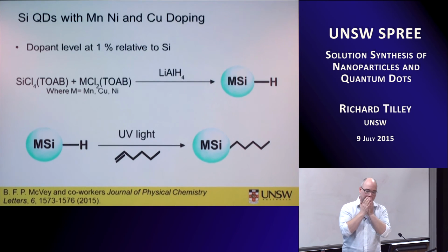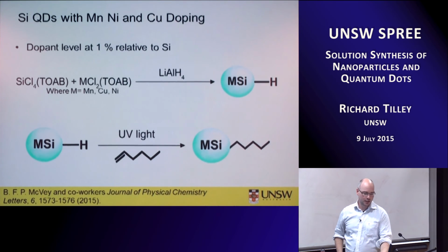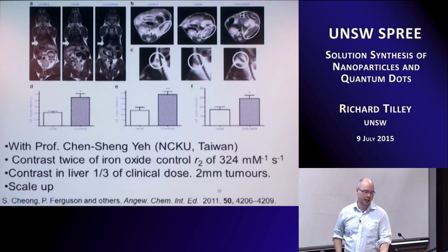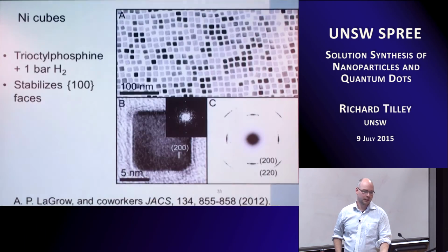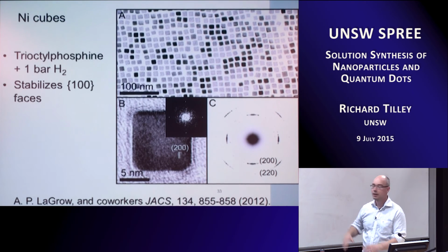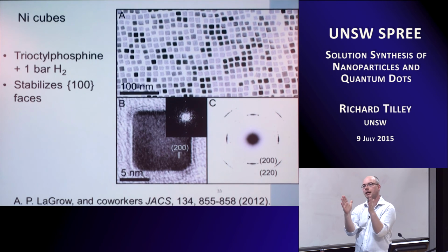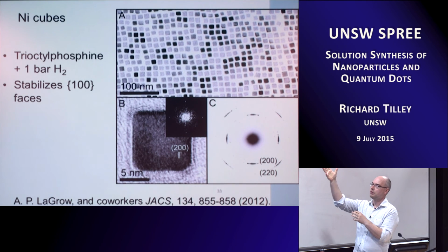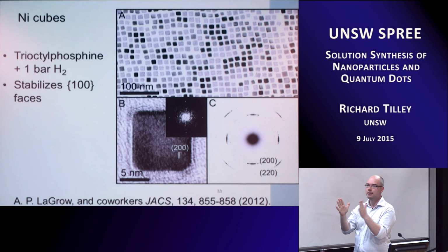So I guess in general what we find, in terms of making the different shapes, typically for this kind of reaction where we're making this cubic shape, there are two regimes where you have surfactants binding very, very strongly to the surface, and then you can end up making quite faceted particles. So, nickel has a cubic crystal structure, the surfactants bind very strongly, keeping to that cubic shape.